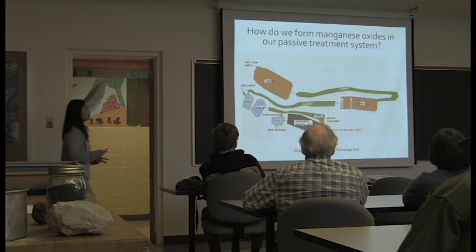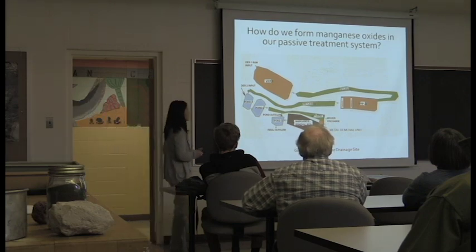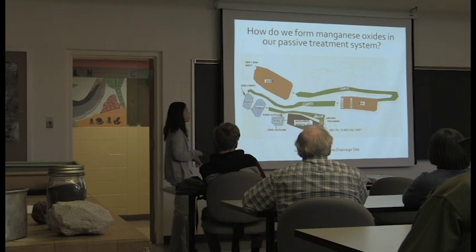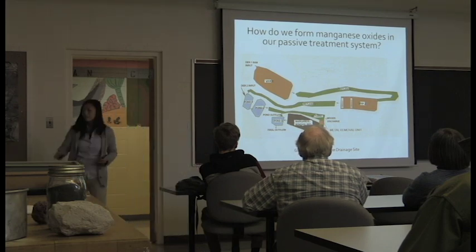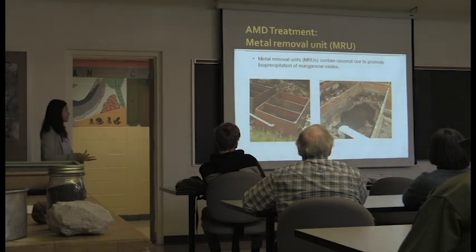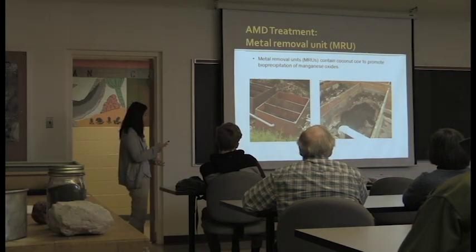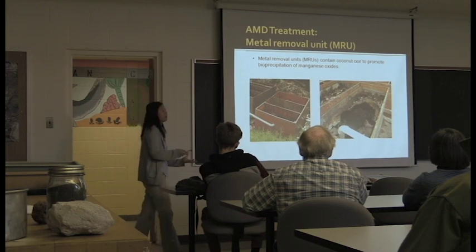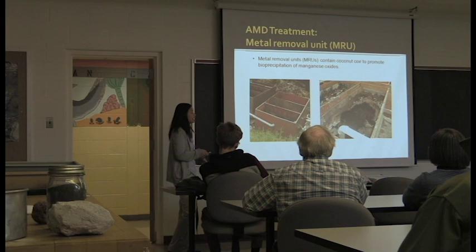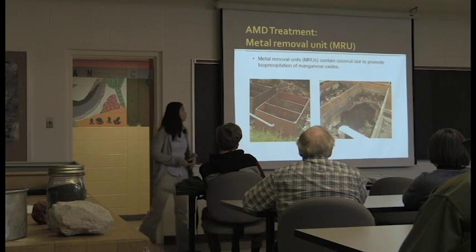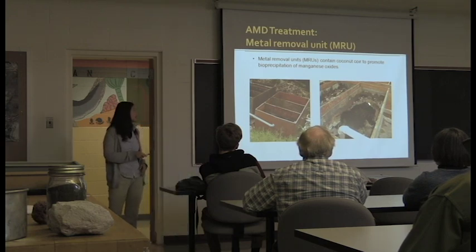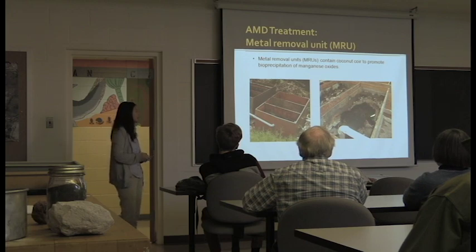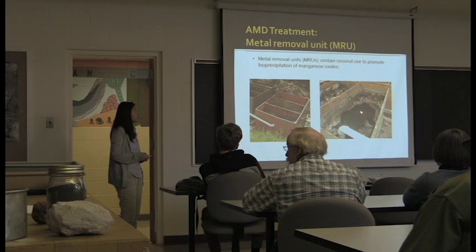The way we do this in the field to promote the growth of bacteria and fungi is we have two different things. We have metal removal units and manganese removal beds. A metal removal unit looks like this. You have this big wooden box, and you fill it with coconut coir. Coconut coir is basically the hairy part of a coconut on the shell. They use this material because it's cheap, it's affordable, and they just throw it in there. So you have your acid mine drainage water coming in here, and then coming out on this side. This coconut coir is usually brown like over here, but when you have manganese oxides precipitating out, they start getting coated in this really dark black color.